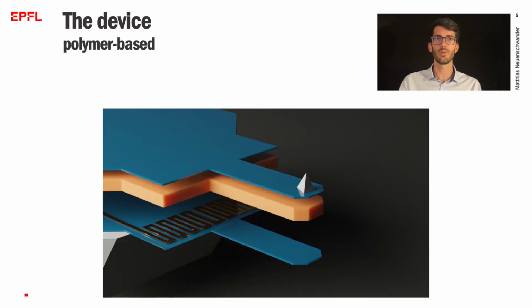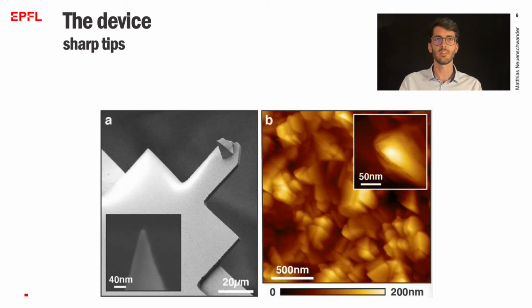Here is an exploded view of one such cantilever. The main structure is made of 3 layers. A thick orange polymer core sandwiched between 2 blue thin films. The polymer is viscoelastic and introduces material damping, ensuring that the cantilever has a low quality factor, something that I will get back to later in the talk. Finally, the cantilever features a sharp silicon tip, something that is primordial in AFM imaging. The sharper the tip, the better the reconstruction of the surface which is being probed.